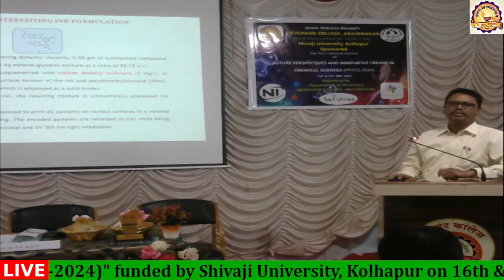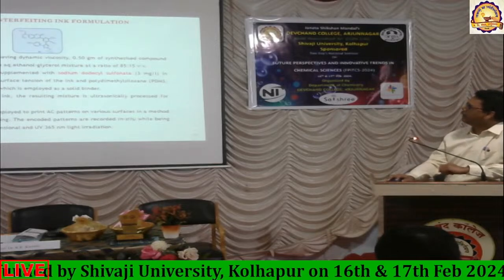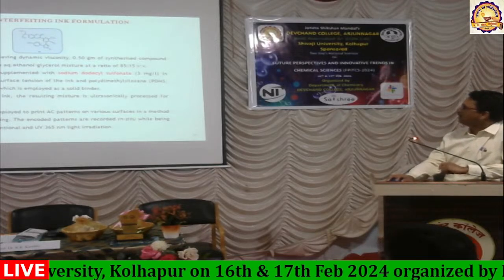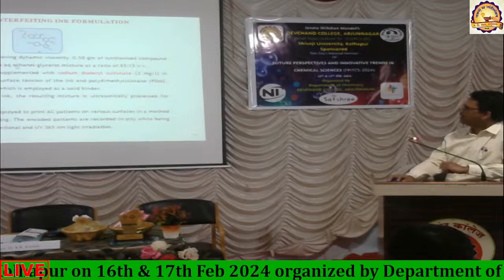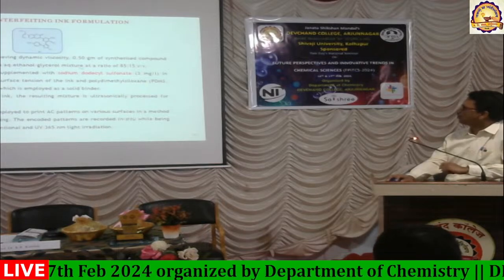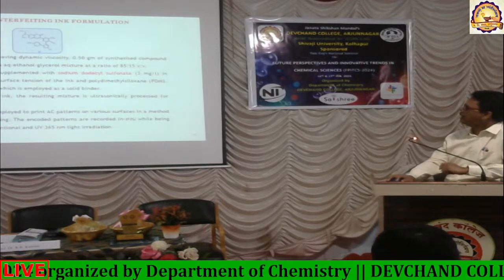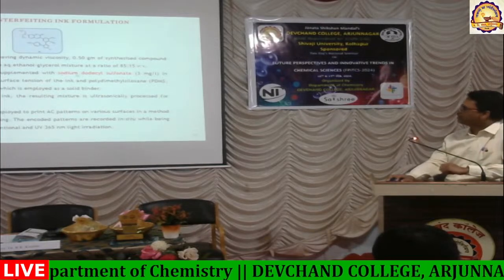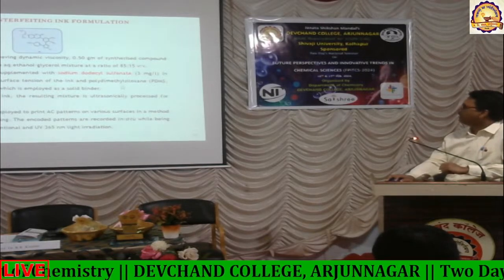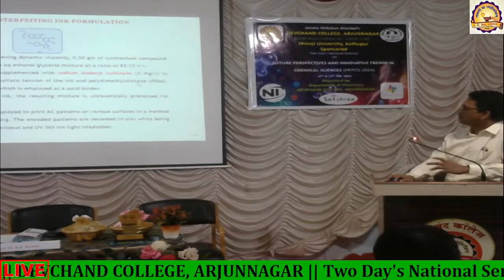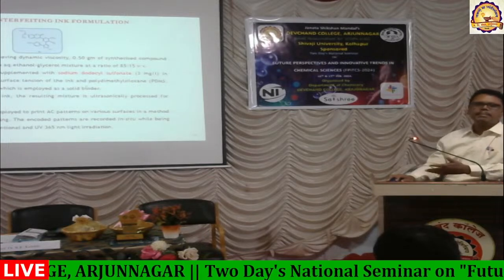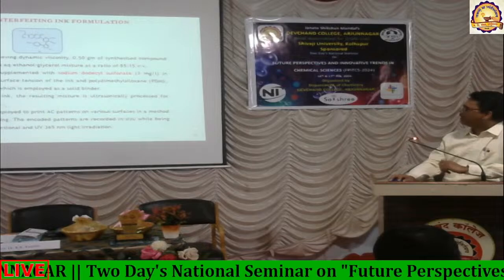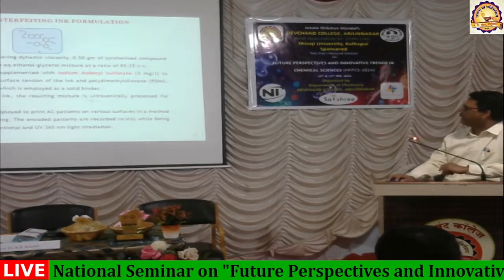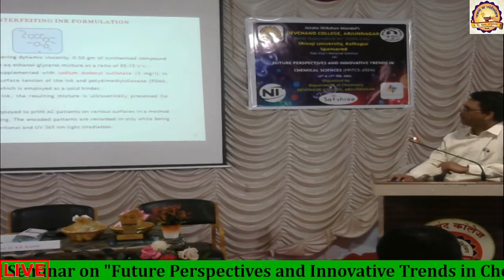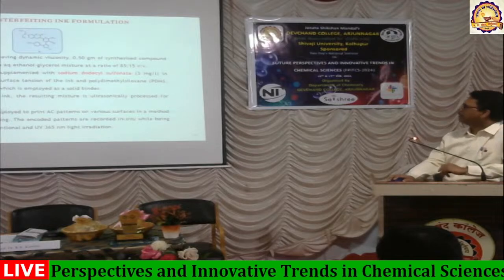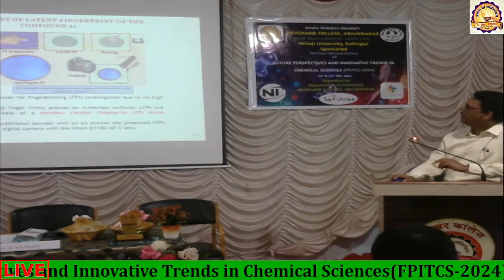How, with the help of the synthesized compound, can we make an ink formulation? For this, they make use of a slurry of the compound with an ethanol and glycerol mixture in an 85 to 15 ratio, and to that they add a surfactant, that is sodium dodecyl sulfate, and then they add polydimethyl siloxane. This was added, and this is the binder. Then the transparent ink was created by ultrasonically processing for 20 minutes, and we got an anti-counterfeiting ink formulated.